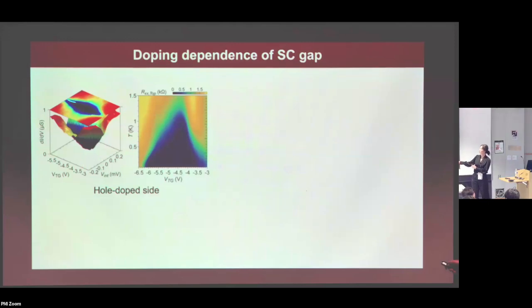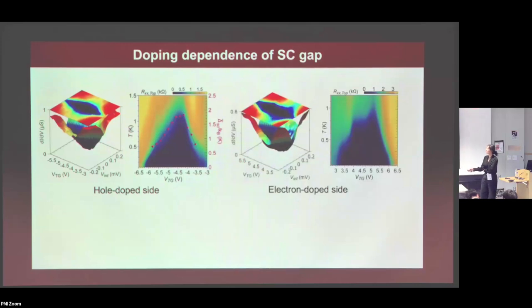And now I want to extract the nodal gap from these tunneling curves and then put it on top of the superconducting dome. And then you can see that it actually follows very well. And it happens again on the electron doped side. You can even catch this little kink in this superconducting Tc.